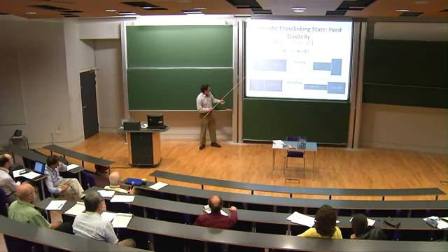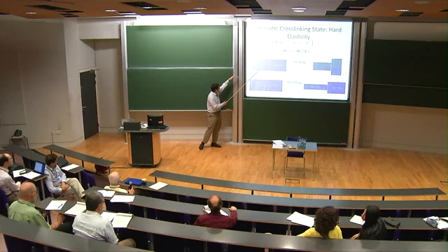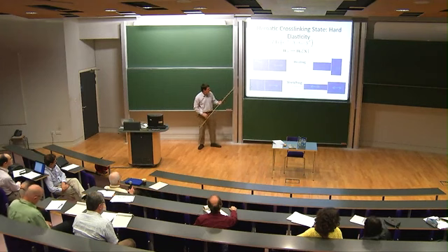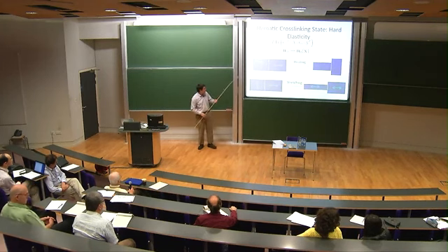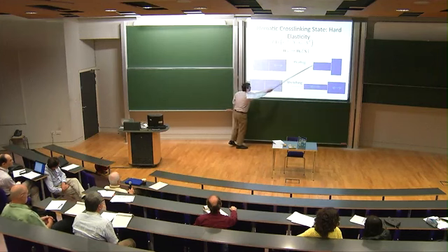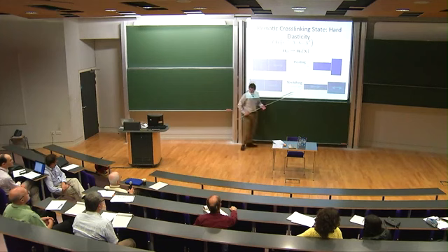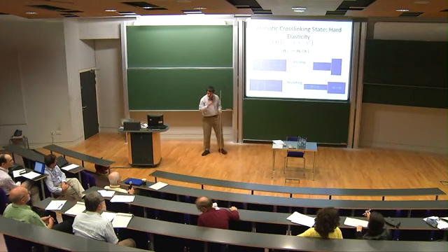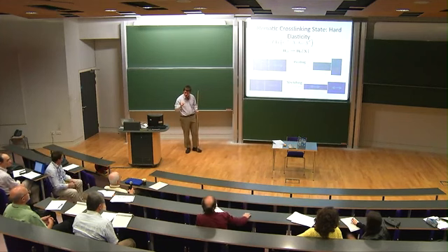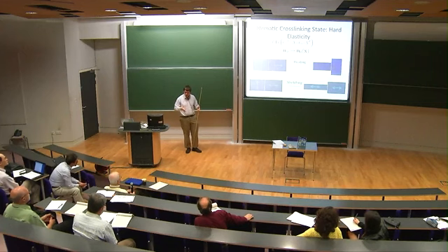So the question you should ask really is, if I go to the high temperature state, then this one wants to contract in this direction, and this one wants to contract in this direction. So you'll get the global soft mode if you can get to a nice high temperature state. And what you see is here you can't, because, again, this one contracts like this, and this one contracts like this, and the boundary complains. Whereas you're guaranteed you can do that in the isotropic crosslinked case because you cross-linked in it, and so you know it exists.